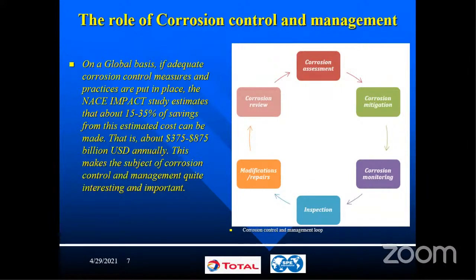First of all is the assessment. You do your corrosion assessment. We put in place the mitigation measures. We monitor the effectiveness of the mitigation we put in place. Then inspection becomes key in the process, because through inspection, we see these mitigations and the monitoring, how does it play with the material itself that we are trying to protect? And then if it works or it doesn't work, you can put in place some modifications or repairs, review your corrosion, and then it's a continuous improvement loop. So inspection and corrosion are tied in the sense that the inspection helps to check if the corrosion mitigation and monitoring systems are effective in the plant itself. So it's a continuous loop.